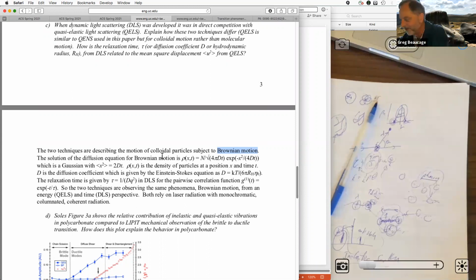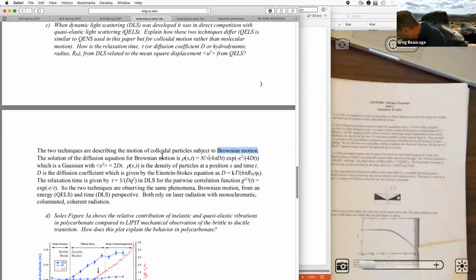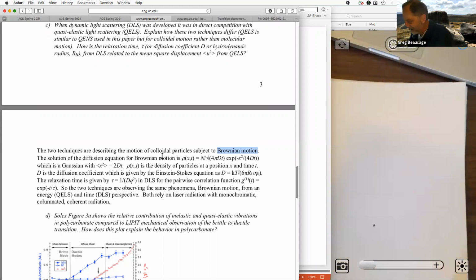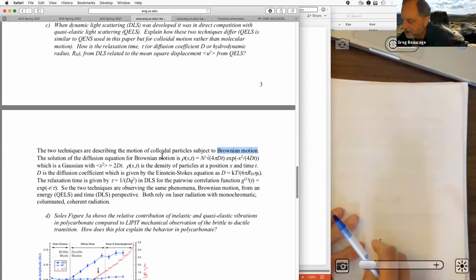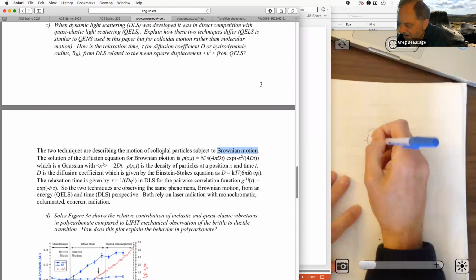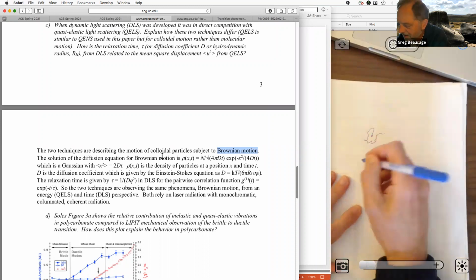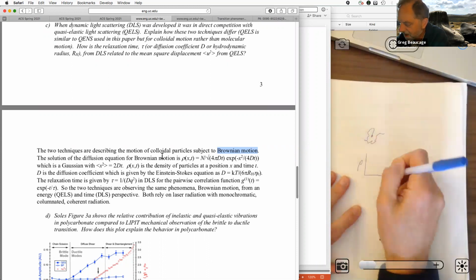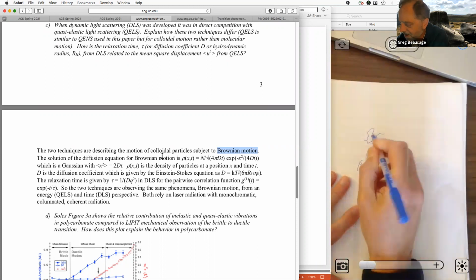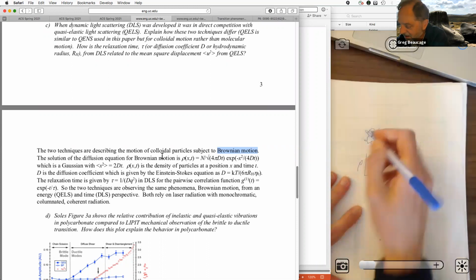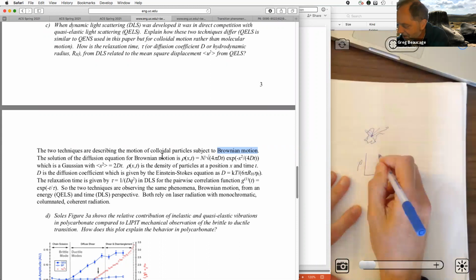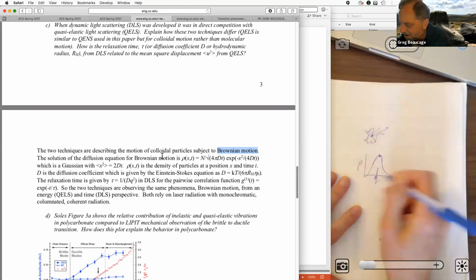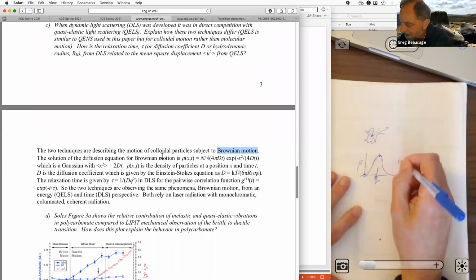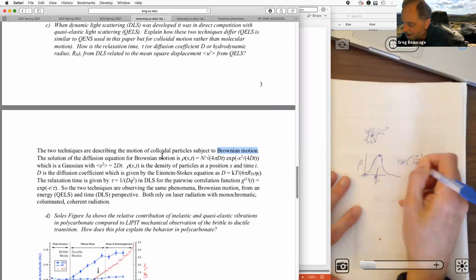Right, so Brownian motion, all these things are kind of linked together. That's the point. They're all kind of confusing, but they're pretty much the same thing. So once you learn one of them, you should start recognizing certain features, and it will make your life easier, right? So you have a particle, it moves around, and then you want to say, well, after all that motion, what's the density of that particle as a function of the position? So it started at 0. And guess what? If it randomly moves around, it's most likely going to be at 0. And it's less likely it's going to go very far. So that probability will drop down. And then it's basically going to follow a bell-shaped curve. Right? So it's going to be exponential minus x squared over 2 sigma squared. That's the bell-shaped curve in 1D.